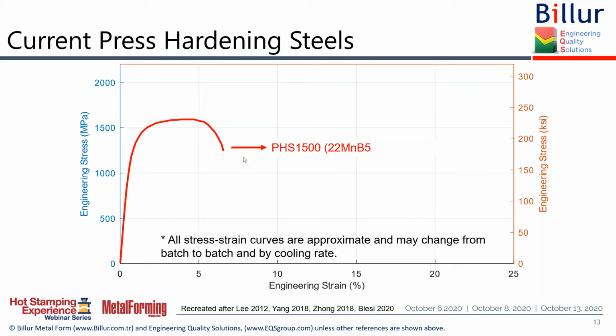There was only one chemistry, but now we have a total of 5 different levels, and you will see several other grades, 20 MnB8 and 22MnB5. I'm sorry for that long name, but we now have 3 different chemistries that can have about 1500 megapascal, which is about 220 ksi tensile strength.